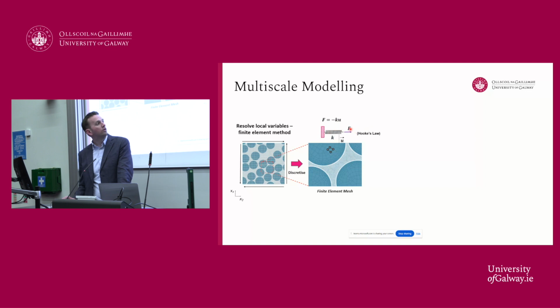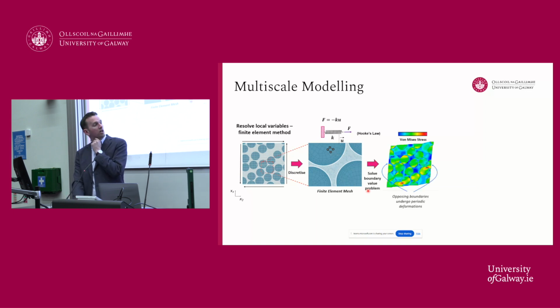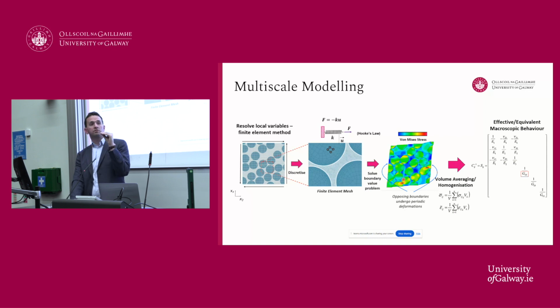For linear behavior, we can use Hooke's law, which defines the relationship between those two springs. If we want more complex behavior, we can use a nonlinear term, which allows us to predict things like fracture. We solve that problem and resolve the local stress happening in the microstructure under a particular loading condition. This gives a picture of what's happening in that structure under a load applied at a much higher length scale. From that, we can average the stresses in that structure and predict our typical material properties for this type of material.